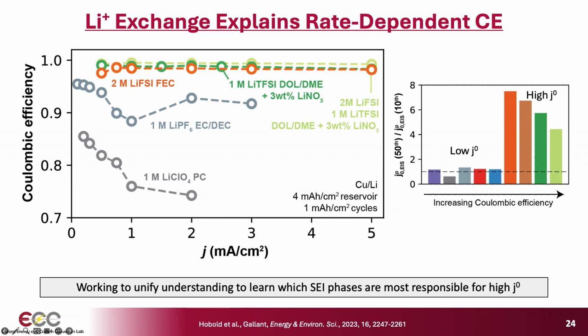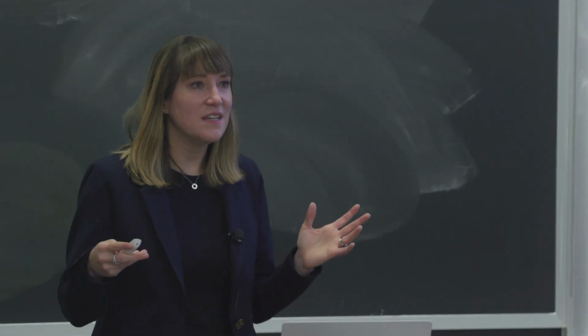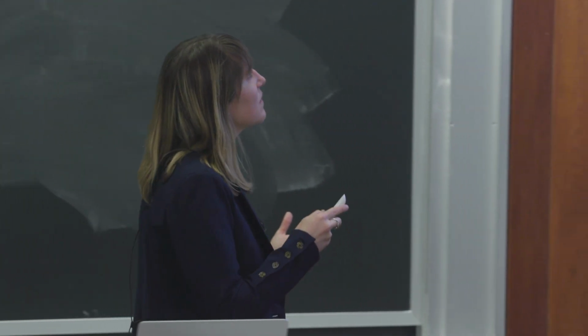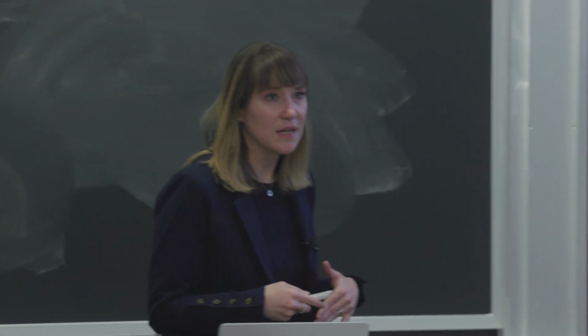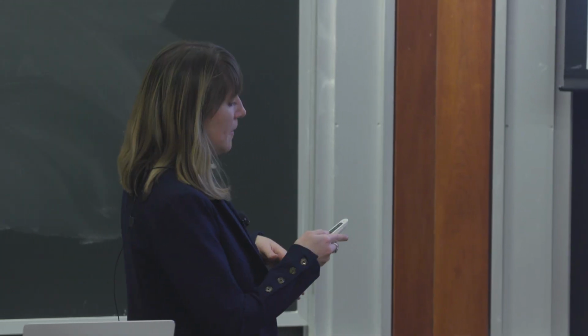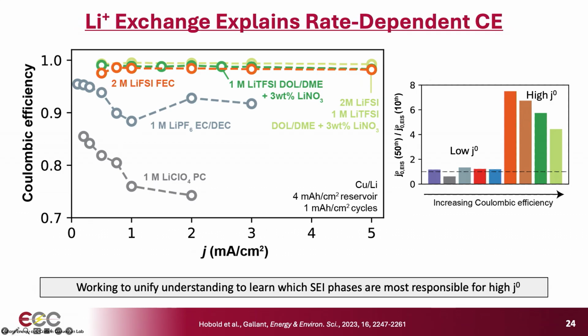Another thing that J naught can tell us practically, we learned that it effectively governs the rates at which we're able to plate and strip lithium. So for electrolytes that have low J naught values, such as these two examples shown in gray, if we try to plate and strip lithium at a rate that exceeds that inherently of their exchange current, we see that the Coulombic efficiency decreases quite a lot, so they become unstable and they can't keep up with the rates that are demanded. On the other hand, if we look at the high J naught systems, we see that we're able to go to much higher plating and stripping current densities and still have high reversibility. Okay, so functionally, J naught really helps govern the rate capability of these electrodes as well.